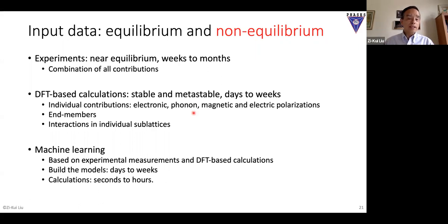And then another one that is even faster is machine learning. Machine learning is where you build a model from the experimental and DFT data. Building the model takes time, about the same as the DFT time, days to weeks. However, as soon as you have built the model, then the calculation is very fast. It takes a very short time, seconds to hours.